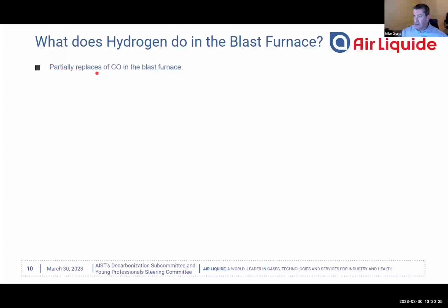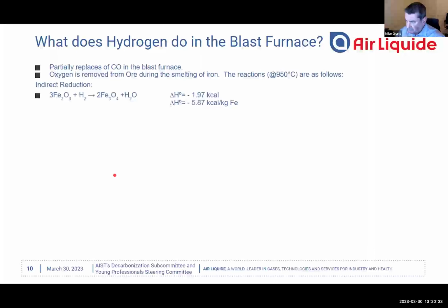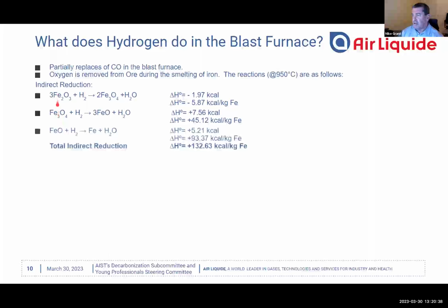Well, you saw in that first diagram I showed you, they had the reduction reactions with CO. Well, hydrogen replaces the CO in the reduction, directly replaces it. And you can see the three main reduction steps being undertaken with hydrogen. And you'll see that these are the energies required for this hydrogen reduction. Now you notice here that there's a net endothermic effect when we do all of our indirect reduction with hydrogen.